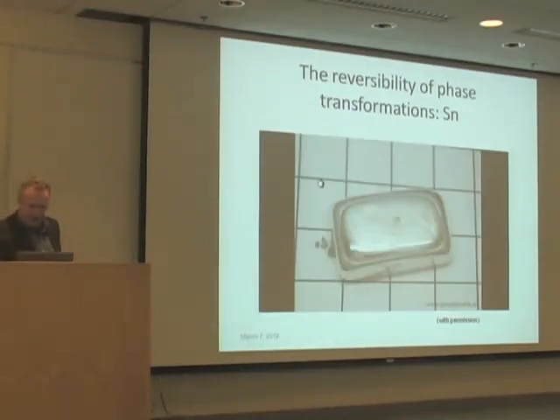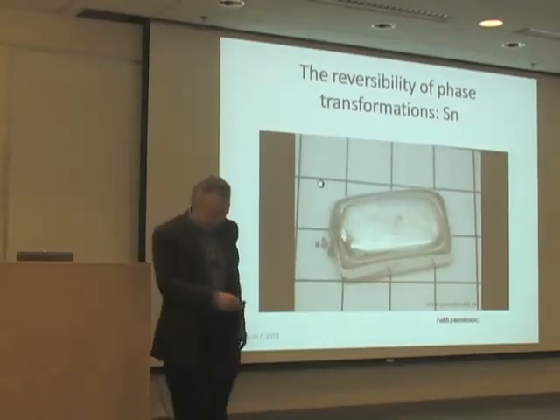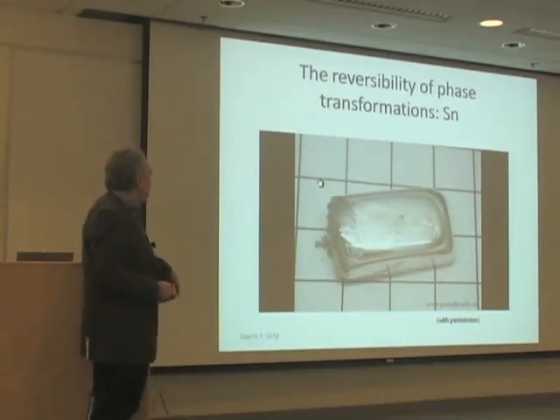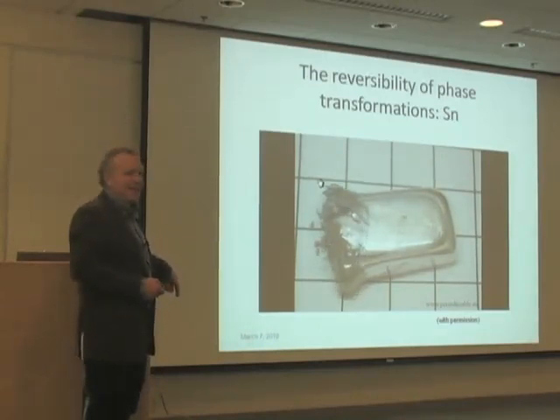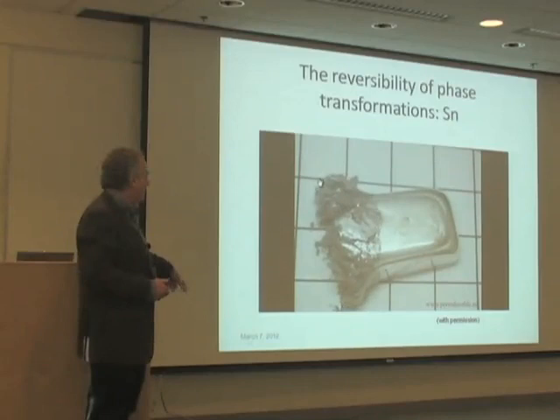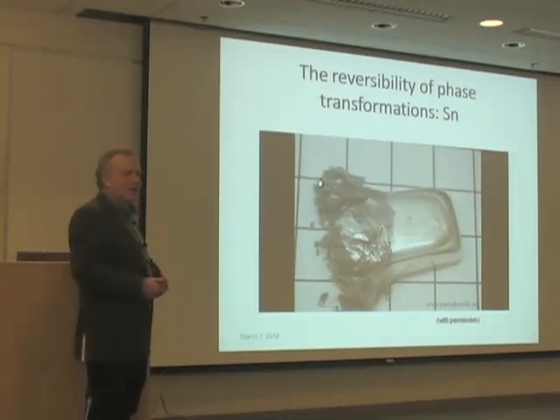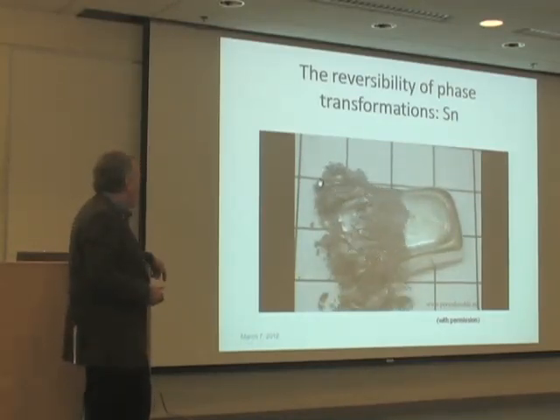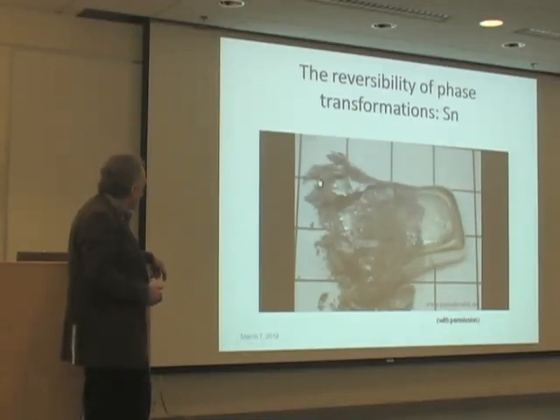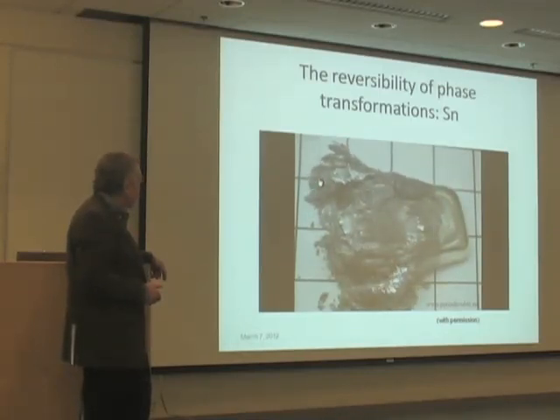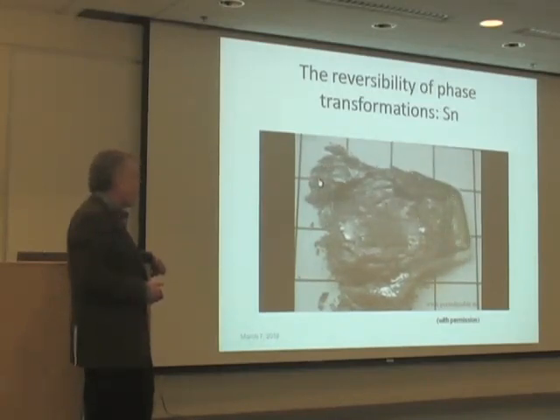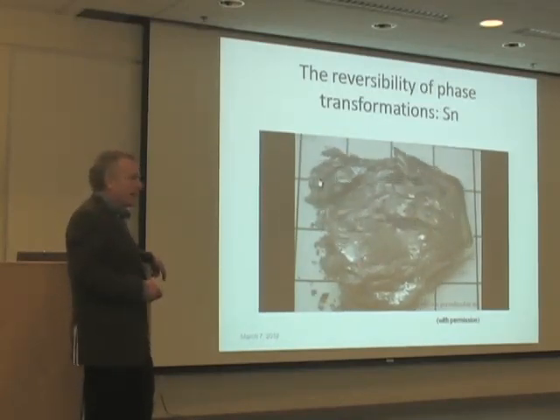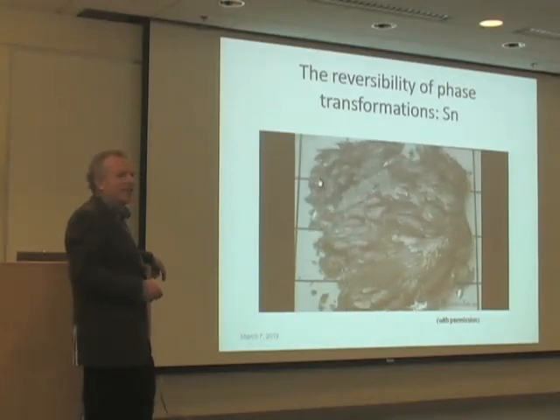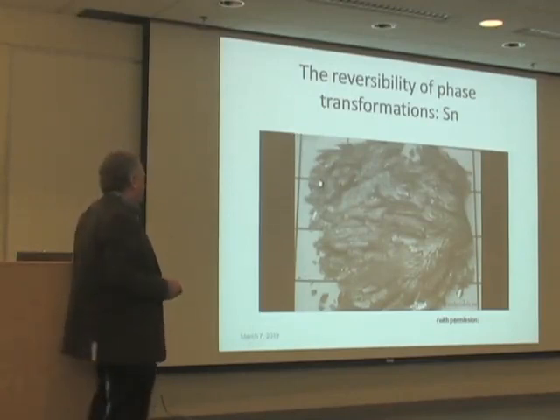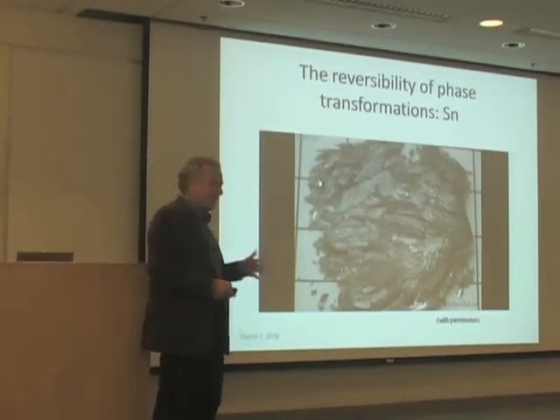And to give you an example of a phase transformation which is not reversible, that's the element tin. So if you cool tin to minus 15 C, this is what happens to it. It undergoes this phase transformation, and it completely tears itself apart. So that's an example of a phase transformation which is really not reversible. If you read papers about this phase transformation, people would say its volume change is big, and therefore it breaks itself. So this is not acceptable. I'll also come back to that point about the volume change.